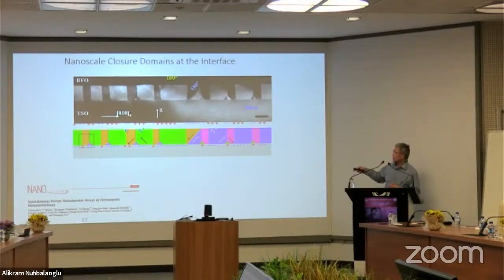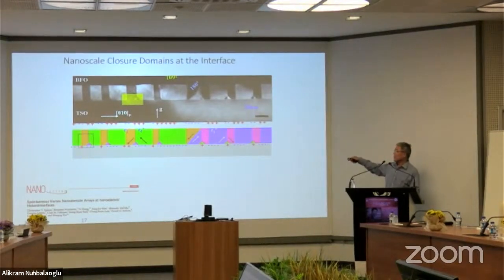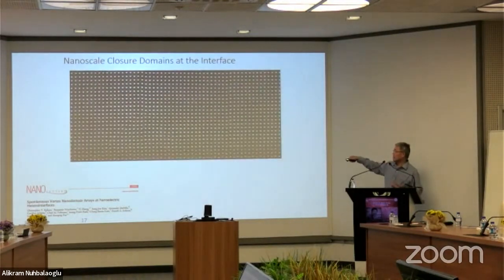But you can see that it's a very interesting phenomenon. If you look at this domain wall, it's very straight, nothing special. But this domain wall is straight, and then you have this bright and dark region, a triangle like here. Now you look along this straight terminating triangle domain, and there's no exception. There must be something going on in the physics to try to understand. Now, if you look at this small region, including two perpendicular vertical domains in combination, one with a defect, one without a defect, and enlarge this with high magnification, you see an atomic resolution image from the region.